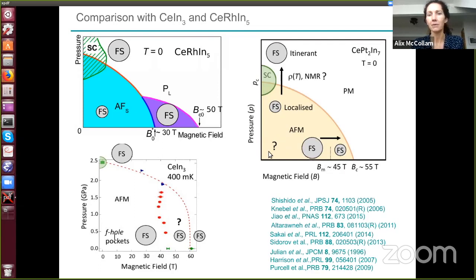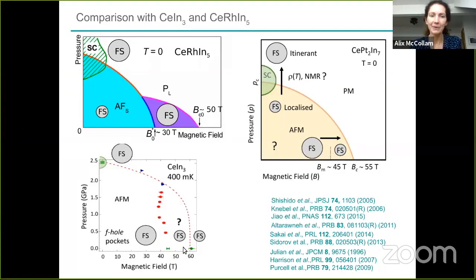So we don't know exactly what the size of the Fermi surface is at ambient pressure and at zero field, but at relatively high magnetic field, there looks like there's a large Fermi surface, at least according to measurements done here, which I'll show you in a moment. And then at higher field, it's thought that around about this field there is a change in the Fermi surface. It looks a little bit similar to cerium indium 3, where at some high field there's a large to small change in the Fermi surface within the antiferromagnetic phase. And then out here, we don't know, we assume it's still small.